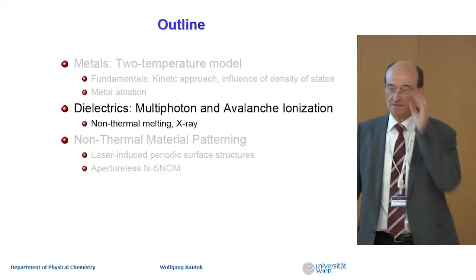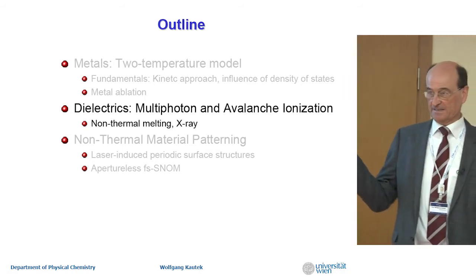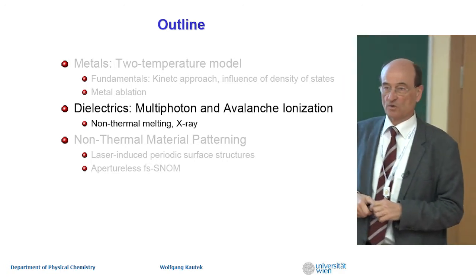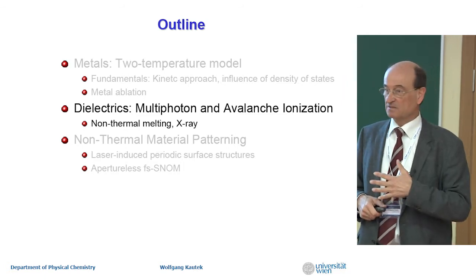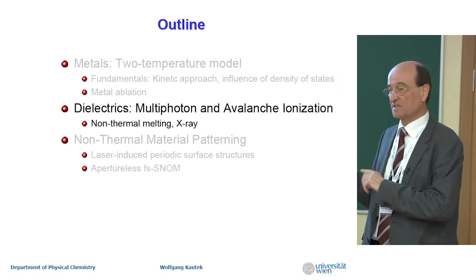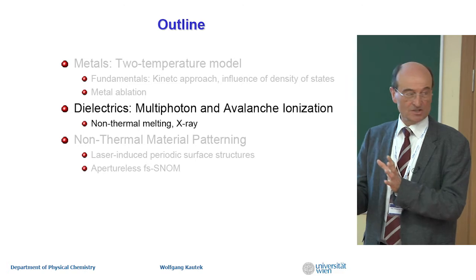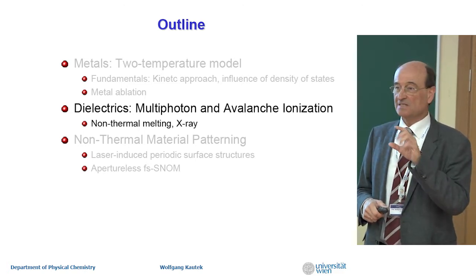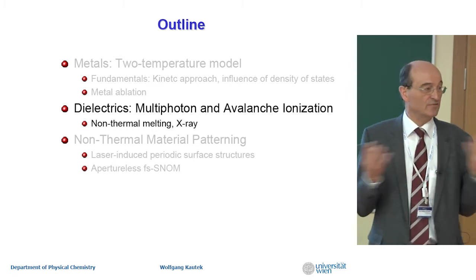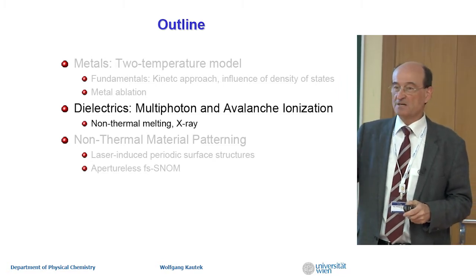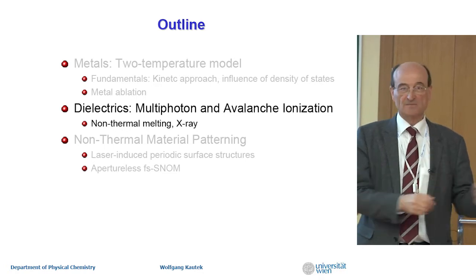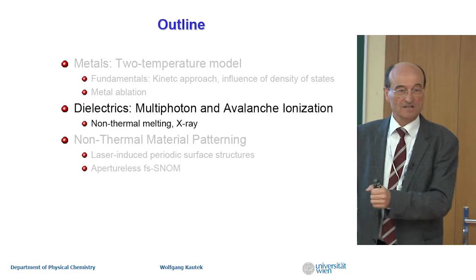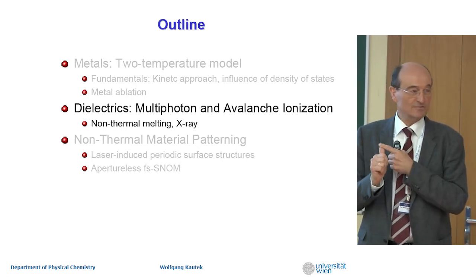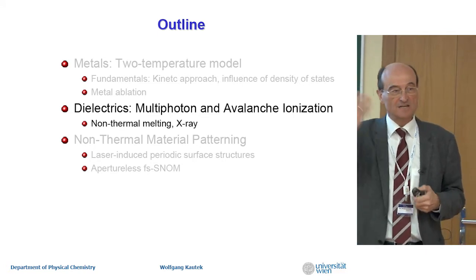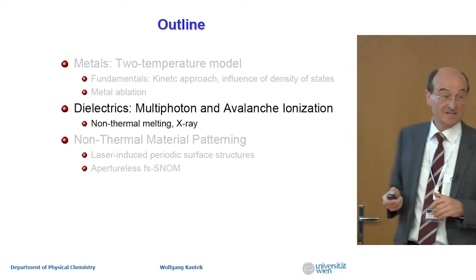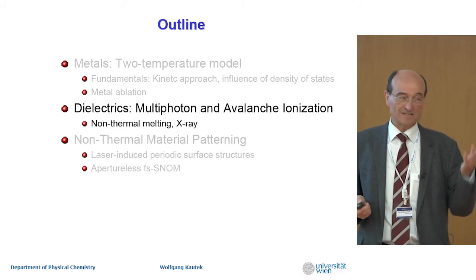Well, the dielectric is something different. The dielectric normally is highly transparent to light, and therefore it should not interact at all. But if we are applying nonlinear optics, multiphoton excitation, or another process, which is called avalanche excitation, there you need thermal electrons which are present due to defects. Remember, a classical crystal and a normal material in engineering are so different because normal materials are highly deficient. They have many defects, and the defects can inject electrons into the conduction band of dielectrics, and then you have some conductivity there. And that is also important for excitation.